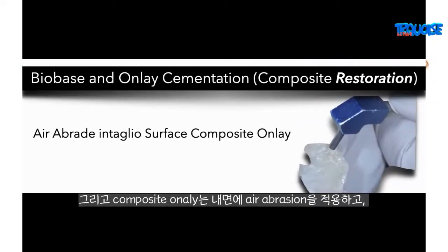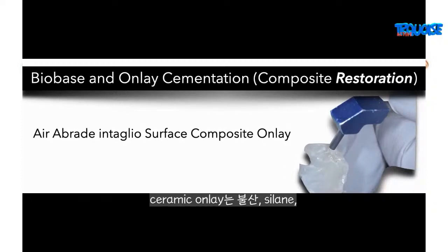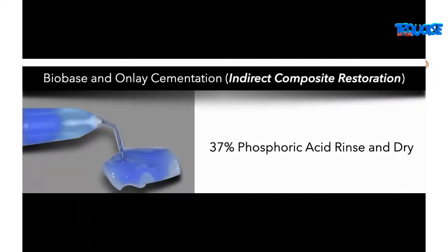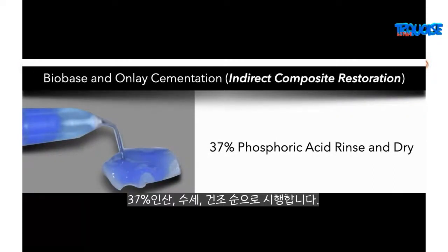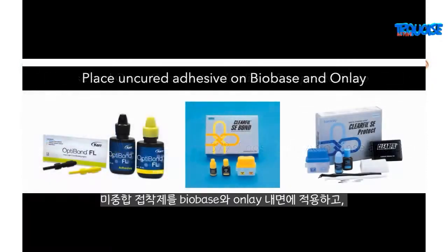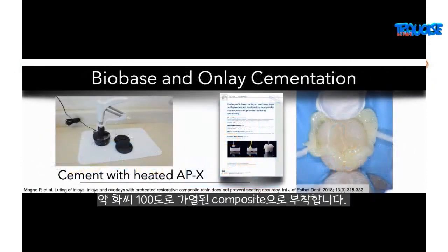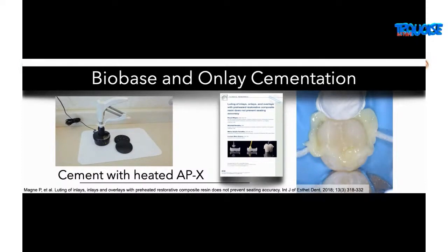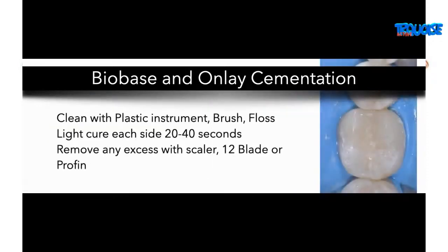Then we aerobrade the intaglio surface of a composite onlay, or treat the intaglio surface, if it's a ceramic onlay, with hydrofluoric acid and silane. Clean that with 37% phosphoric acid, rinse and dry. Place uncured adhesive on the biobase and on the intaglio surface of the onlay. And then we seat that with heated composite, heating the composite to about 100 degrees Fahrenheit. And that makes it very easy to clean up using the heated composite cementation. Very easy cleanup.